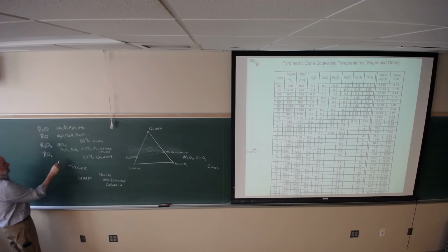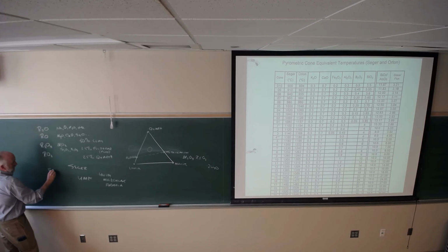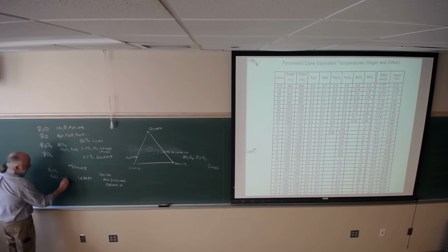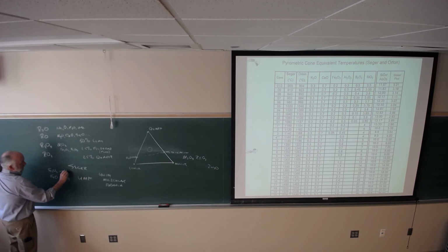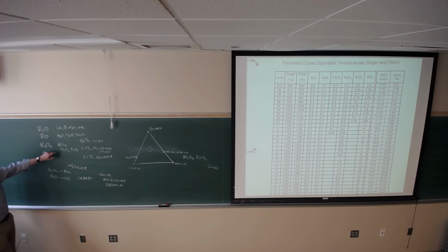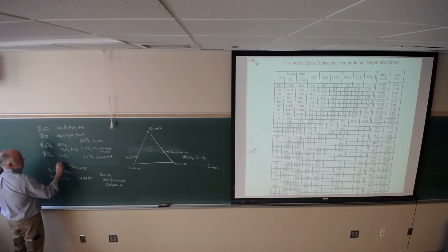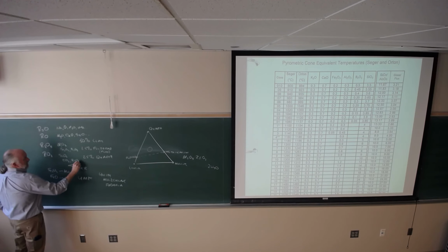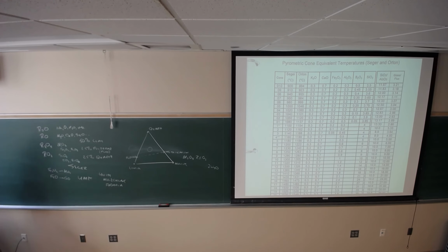We'll address that. Iron, though, shows up 2 ways: Fe2O3, FeO, in reduction, right? And FeO behaves like calcium, and Fe2O3 behaves like alumina. So what really should happen is that he should treat Fe2O3 as FeO. It should go up here and act as a flux. Okay, fine. And then RO2, you've got silica, that's the big one. Then you have titania, you have zirconia, okay, etc. So because he grouped them that way, then he looked at iron that way, and it doesn't help us understand what's going on. So he gets down to cone 1, that sounds great. And then somebody came in and said, you know, we'd really like to measure temperature below cone 1. So then O1, O2, O3 were developed later.